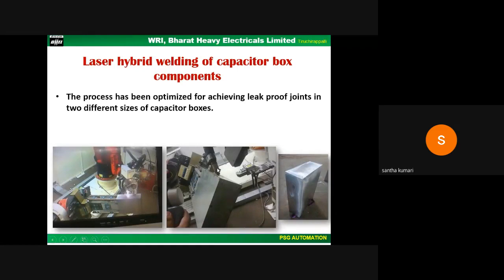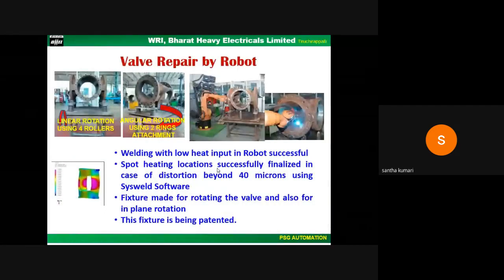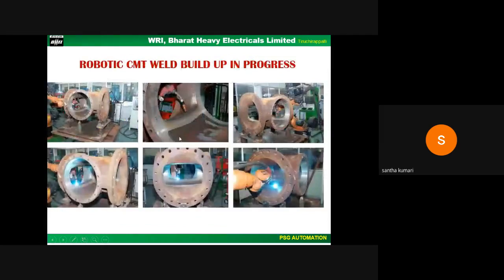This Robo has also been used for repair welding of valve bodies, that is machining, this building up of material. We are now talking about 3D printing, all these things. We used our Robo with the CMT power source because we needed a low heat input process for repair of this valve body component. A special fixture has been developed for positioning the valve body to integrate it with Robo. We were able to do this repair welding with Robo with this CMT process.